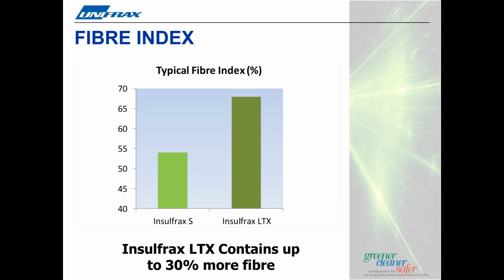This reduction in shot content and size means an increase in the amount of fiber. This is what we call a high fiber index. Insulfrax LTX blankets contain up to 30% more fiber when compared with Insulfrax S blanket. This equates to a 20% reduction in thermal conductivity, enhancing the insulating properties.